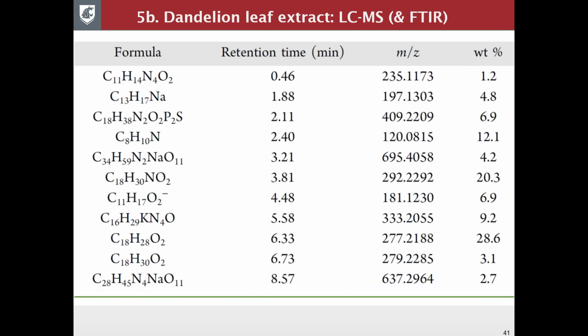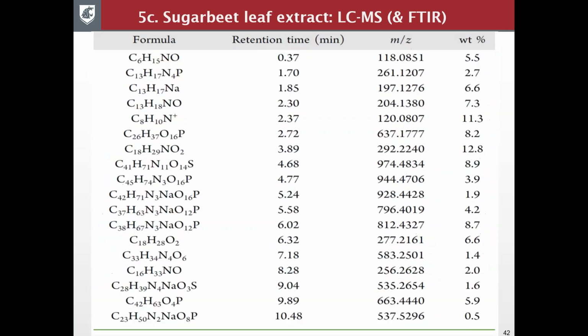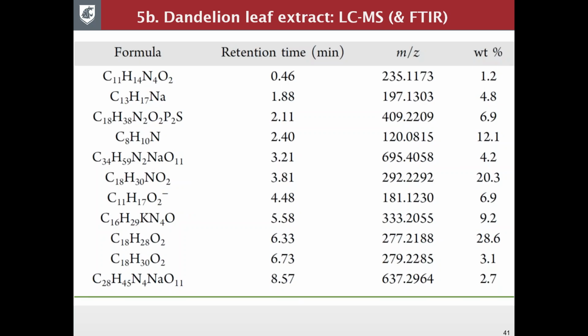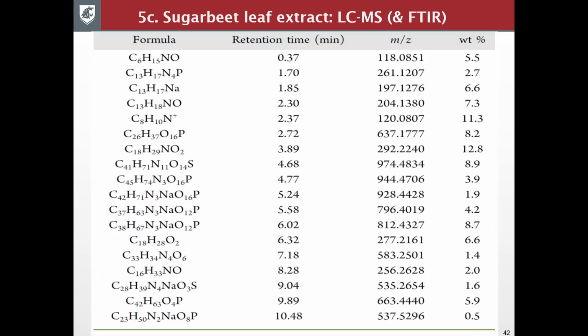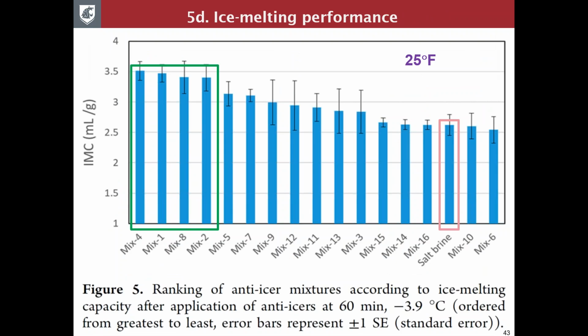And we use some of these tools to identify what kind of chemicals are in them. As you can see, these chemicals tend to have a molecular weight no more than 1,000, and they contain a lot of organic phosphate or nitrate or oxyanions. So two different types of feedstock, dandelion versus sugar beet. Of course, the chemical products or green chemicals are different. And we tested the different mixes with the 23% sodium chloride. You can see, statistically speaking, we identified 4 mixes in this green box, which had much higher ice melting capacity than the salt brine control, which is in the pink box at 25 degrees Fahrenheit.